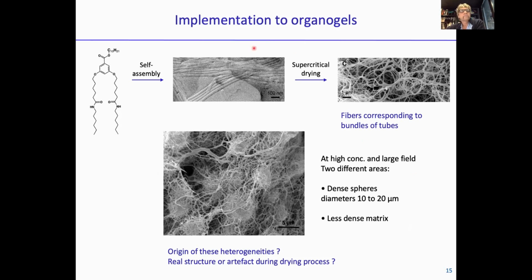So this is what we did. We start from our gelator. We self-assemble it in solvent, and this is a freeze fracture micrograph of what I showed you already. So you can see the tubes. And then by supercritical drying, this is what we get. So these images are not the same, because you see here the scale is much higher. And here, these objects that you can see are not single tubes, they are bundles of tubes. Okay, and even now we can observe this aerogel at larger scale, and you can see here what we obtain. So when you look so, now you can see at larger scale that we have two kinds of areas.